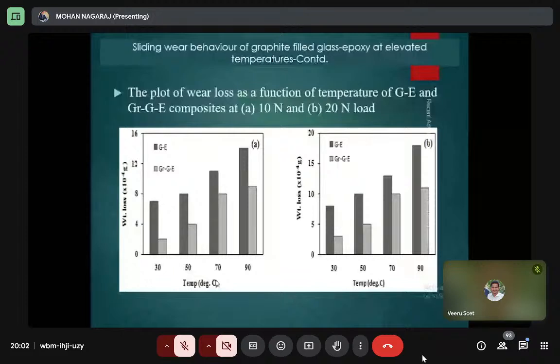Here we studied up to 90 degrees Celsius. We can possibly go up to 200 degrees Celsius, depending upon the matrix. Here, since epoxy is the matrix we are using, the epoxy matrix withstands up to its glass transition temperature of 150, 160 or 120 degrees Celsius. That's all. If you use a phenolic composite, it is possible to use it at 300 degrees Celsius, in engine components.